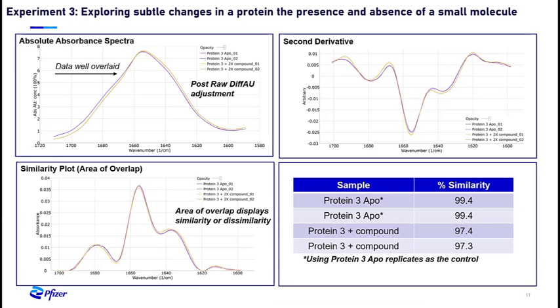In this next slide, you can see that the data is well overlaid in the absolute absorbance spectra, which, if you remember, is a normalization of the raw data. To the right, we have a second derivative plot, which begins to clearly show the features of protein secondary structure for this protein. The change between the apo and ligand-bound protein is not as dramatic as in our previous experiment, but you do observe some change. Below, we've again calculated the percent similarity among the samples using the apo as a control. And to the left of this is our similarity plot, clearly showing minor change in beta sheet content at 1638 with a slight increase, albeit subtle.